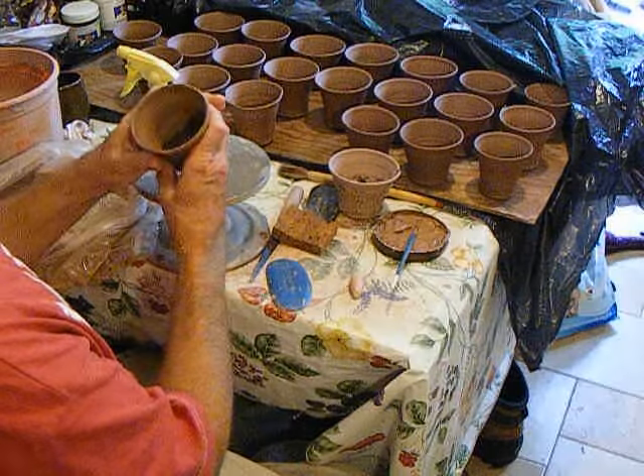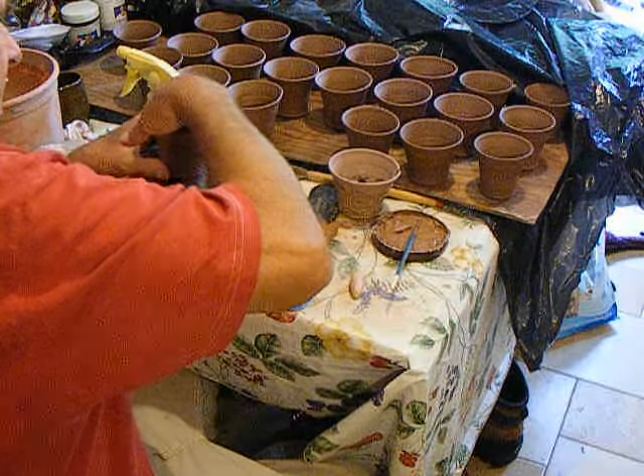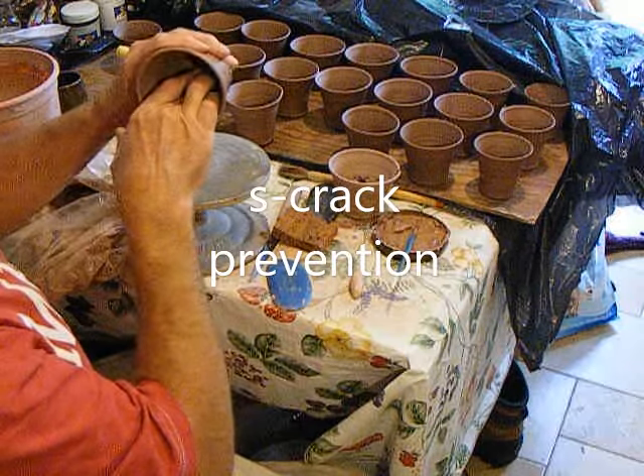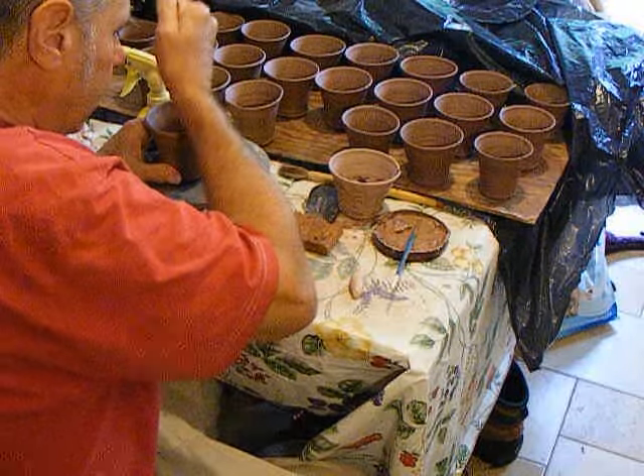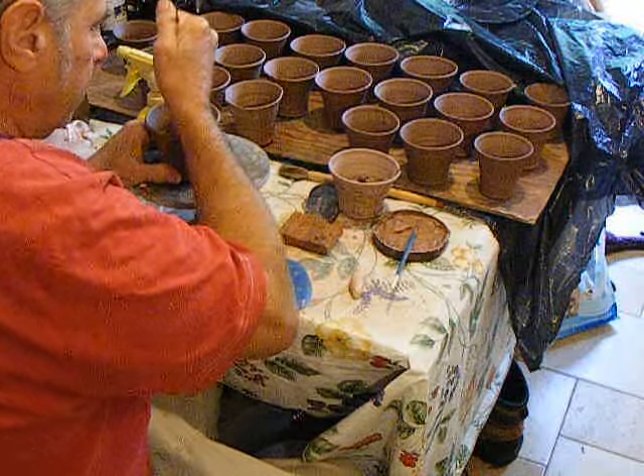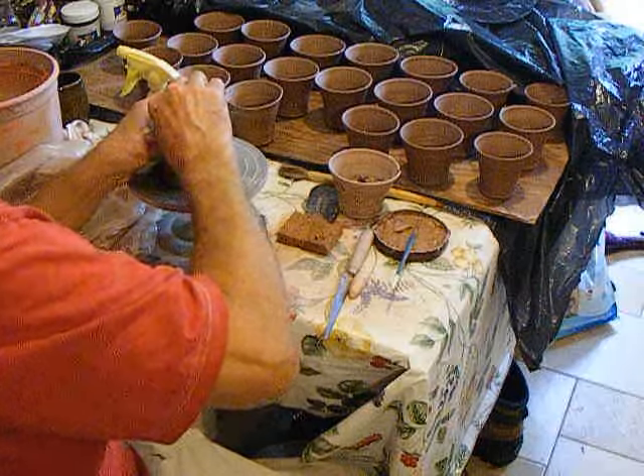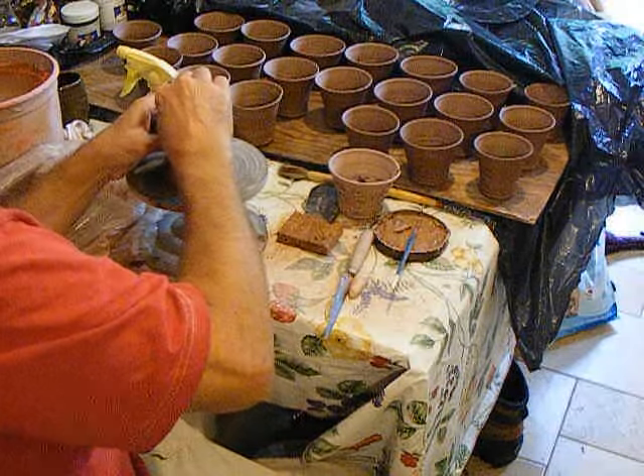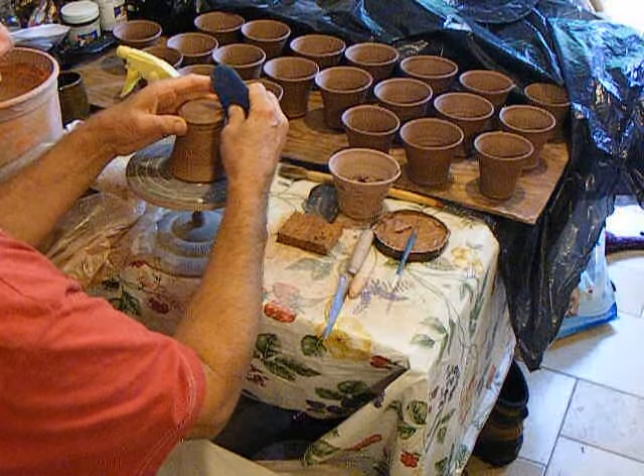First we'll see if they're round, and then the problem is S-cracks. I've been pushing down in the center in a circular motion. If they're a little bit too stiff, I've been taking the flat edge of the potter's knife and pounding down. This is an extra attempt to avoid S-cracks and compact that clay a bit. I've done my best to cut these cleanly off the wheel, and I go over the bottom with the rib to make it very smooth — but really what I'm doing is compacting the bottom, hoping to avoid any S-cracks.